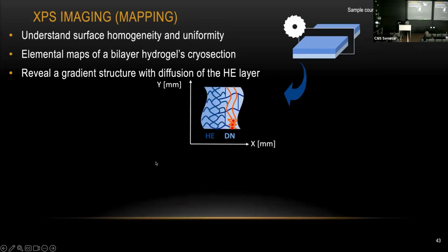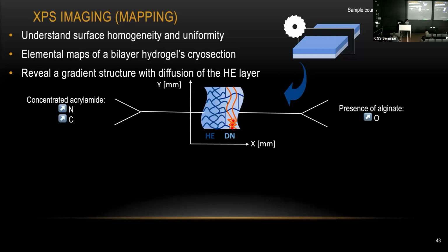So by getting all those spectra, we can also do some kind of imaging. Some people call it mapping. It can pretty much help you understand your surface homogeneity and uniformity. Here is a sample from the Mooney lab here. It's just 2 pieces of hydrogel, and in one piece of hydrogel we try to have some acrylamide content inside, which means it's high in nitrogen and carbon. And the other piece of hydrogel we try to have some alginate inside, which means it's high in oxygen.